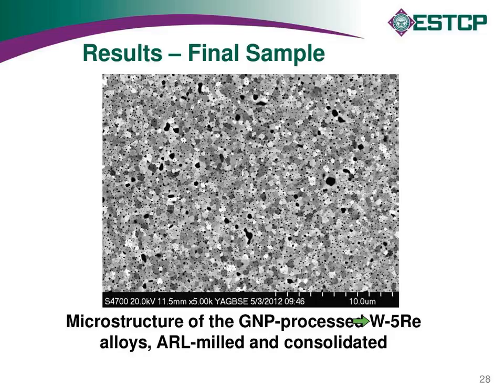We were working with Brady Butler over in the materials division, and he was looking at tungsten rhenium alloys that were made by mechanical alloying kind of processes. So we wanted to look at a much more intimate mixture of the two materials by the glycine nitrate process. So that's what these powders were, and then they were de-agglomerated in Brady's wet mill and then sintered. And we got a pretty good material. It's just barely submicron in the end, but close to full density.